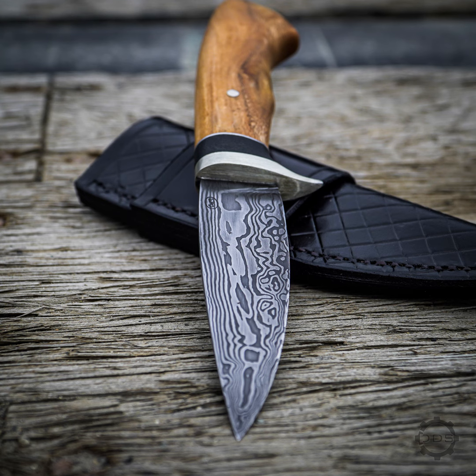Something that you will notice, and you should notice with a quality Damascus blade, is you should see the layers compress towards the tip. Yep. So they're wider towards the back, and they compress towards the tip. And if you don't see that, the smith hot cut the tip, which is a much easier way of forming the tip. Okay. If you see them compress, that tells you that the smith took the time to actually forge the tip into his blade. Right. And so it wasn't just cut out of like a big chunk.